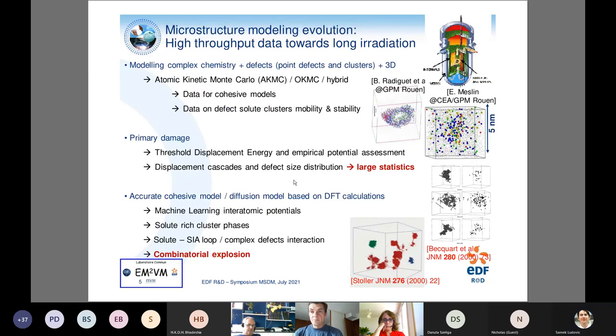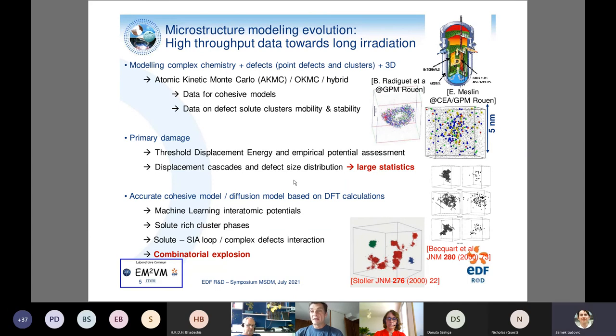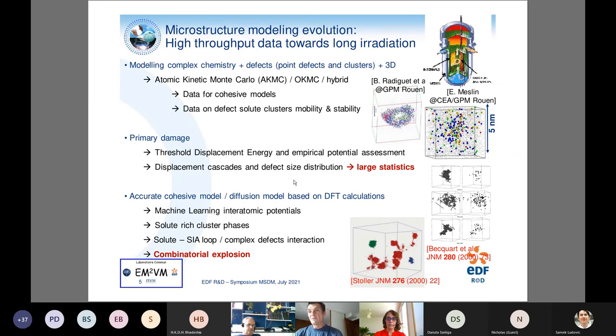We model the complex chemistry as close as possible to a real steel, including point defects — vacancies and interstitials. Under radiation, the concentration of these defects is several orders of magnitude higher than at thermal equilibrium. The two main challenges are building a cohesive model for the kinetic Monte Carlo and properly characterizing the primary damage, since point defects interact strongly with solutes, creating many possible interaction configurations that require extensive atomic calculations.